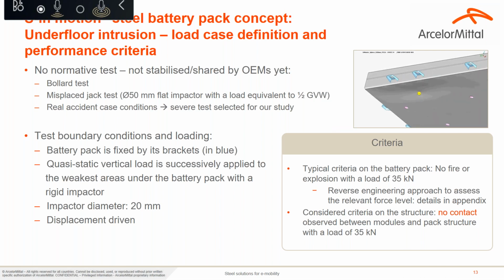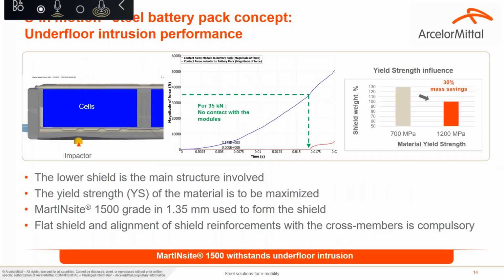We have studied data of a real accident case condition, and we have selected this in our study. It represents an impactor of 20 millimeter diameter, so a small object, and you have to respect a load of 35 kilonewton without fire at the end. That's why we have also taken into account in our condition no contact between the structure and the modules, sorry, the cells. So in this slide, you can see how the shield behaves, and that is the main structure involved in this load case. Again, the yield strength of the material is very important, and is even more important than in the previous case.